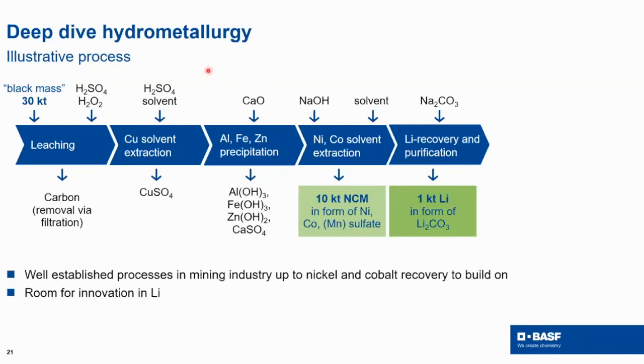The process starts with a leaching step. In that leaching step, the black mass is leached with sulfuric acid and hydrogen peroxide. The second stage is then an extraction of copper via solvent extraction. Afterwards, all these impurities are precipitated out by raising the pH value. So very basic chemistry. People might remember the first year at university where all this is also discussed. After that impurity precipitation, there is a sulfuric acid solution containing nickel, cobalt, manganese, and lithium. And nickel, cobalt, and manganese are taken out through solvent extraction. And the lithium in a typical recycling process is afterwards precipitated out as lithium carbonate.